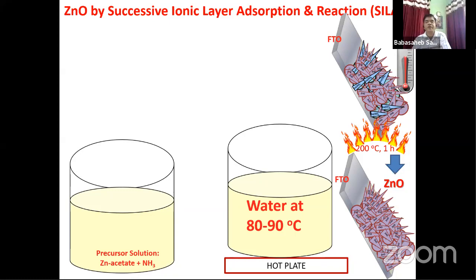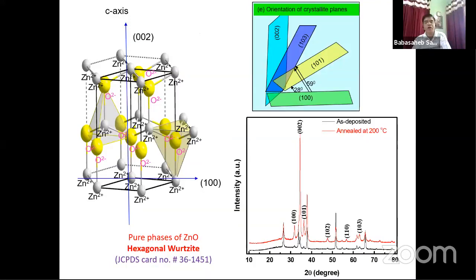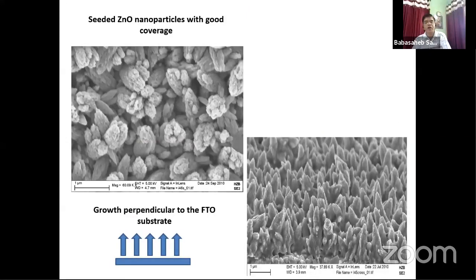And this is the X-ray diffraction pattern where you can confirm what structure the obtained zinc oxide has. We found that it has a hexagonal wurtzite structure of zinc oxide with orientation along the 002 plane, that is the C-axis orientation. In the SEM image, you can see this is a seeded layer of zinc oxide grown on the FTO coated glass substrate. You can see the growth is perpendicular to the substrate surface, that is the C-axis orientation. We have used this as a seeded zinc oxide, which is not really compact, but it can create some nucleation sites for the further growth of the nanoporous zinc oxide.